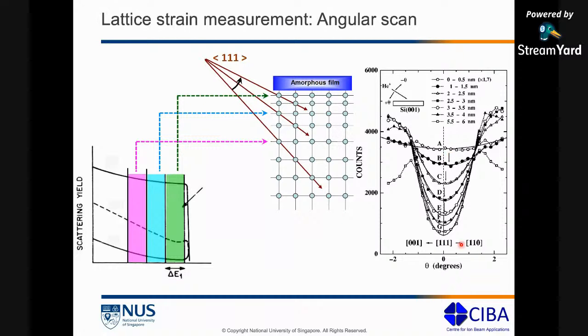Once we have these set of curves, then we look at the lowest, the first curve here, the G, and the local minima of G, and compare that to the local minima of curve A, right? So curve A corresponds to this region here near the interface. Curve G corresponds to this region here in the bulk. So we are essentially comparing the channeling from the bulk to the channeling near the interface. So we're comparing the local minima of G to the local minima of A. And by looking at the shift in the local minima of A from G, we can then get an estimate of how much strain we have in the sample. And the direction of the shift will also tell us whether it is compressive or tensile.